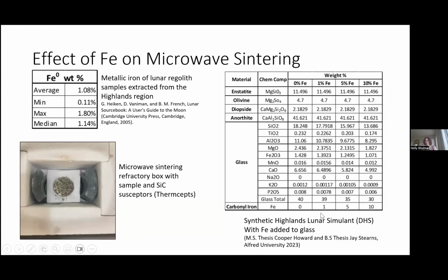And I also want to point out that 1% iron, 1 weight percent in the glass, is the closest match to the baseline material because we're taking glass out as we're adding iron. Okay. So just pointing that out. Also, this actually should be SiO4 for olivine. So olivine, I'm showing this as Mg2SiO4. Olivine actually has iron on the magnesium site, but this end member is really called forsterite. So it's variable how much iron you can have on that site. Just to make things very simple as a baseline, we decided not to use any iron anywhere except in that glass.